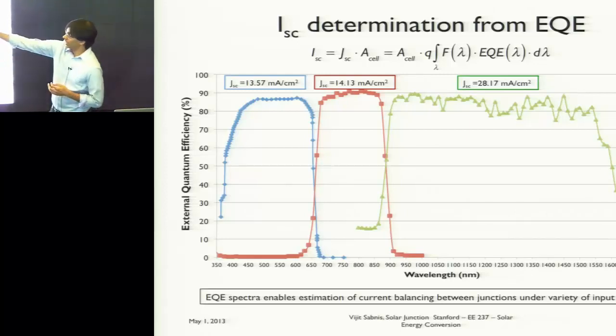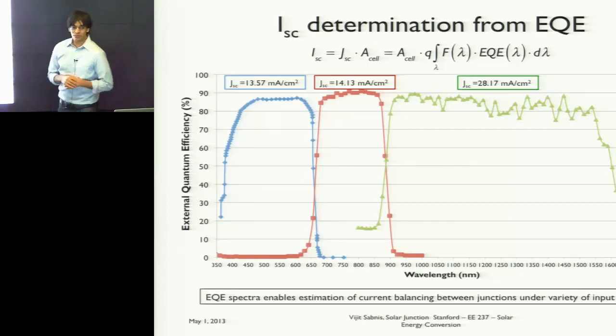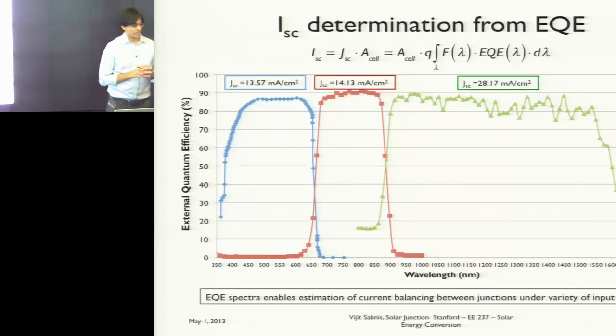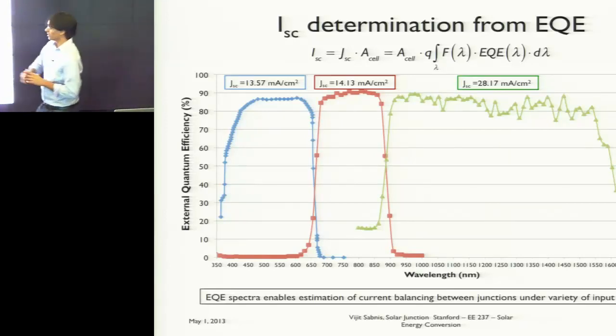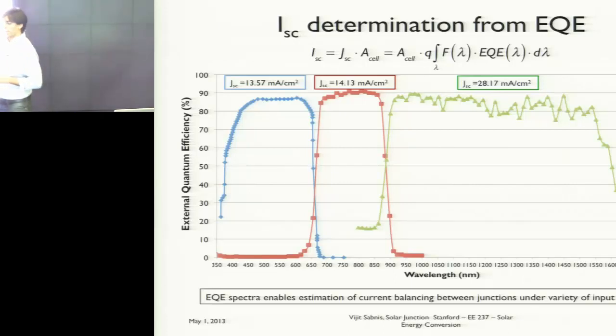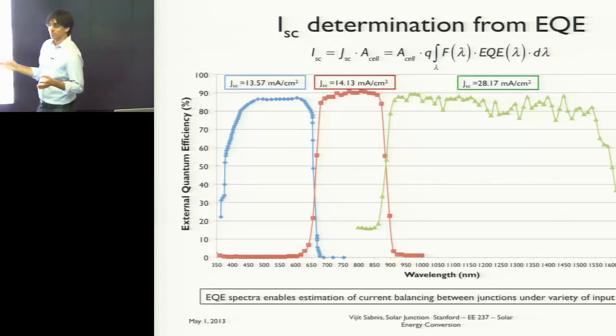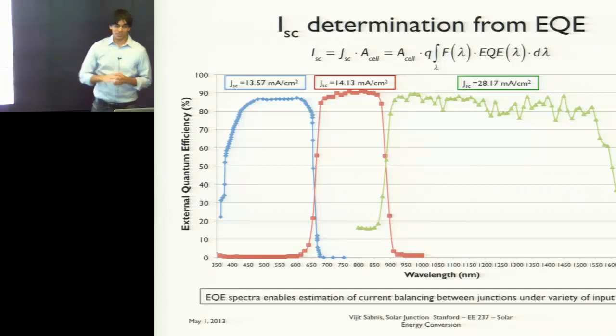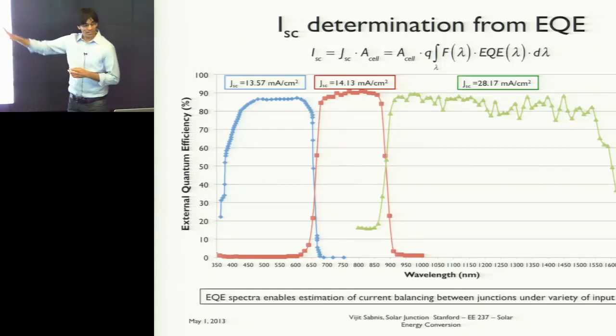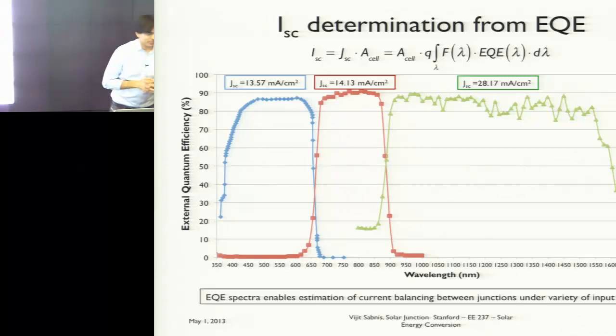If you integrate each of these individual junctions, you get somewhere around 14 milliamps per square centimeter. Now, interestingly, this bottom junction has a band gap which is much wider than it needs to be. It produces about twice as much current as each of the top two junctions. And this is actually measured data.